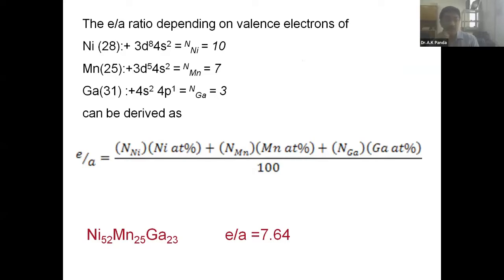When we work with alloy chemistry, the e/a ratio, electrons per atom, is very important. Let us go on with how it is calculated for a typical nickel manganese gallium composition. It is typically 7.64, using the atomic percentages and valence electrons.